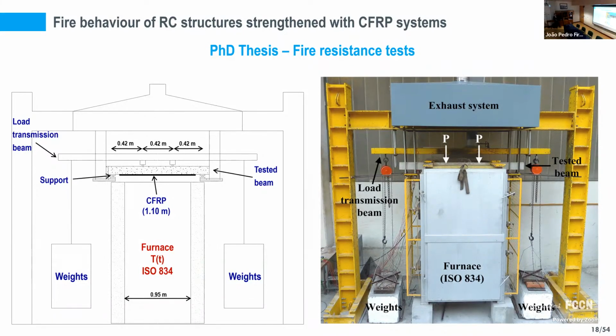And here is the fire resistance test setup that we have here at CERIS laboratories, where we use a furnace that follows a typical standard fire curve. This furnace applies a heating curve to the bottom part of the member that is being tested, and the member is subjected to the fire action and simultaneously subjected to a constant load. In this case, we adopted a 4-point bending configuration, simulating a typical load scenario that is expected in a fire load combination.